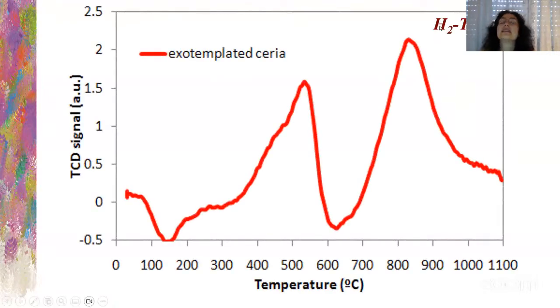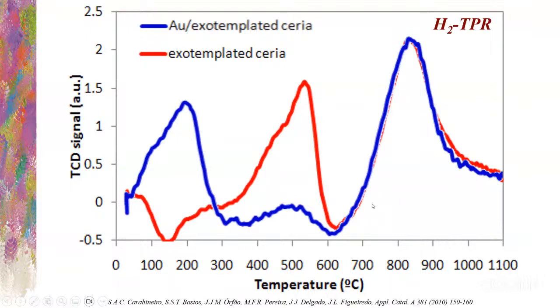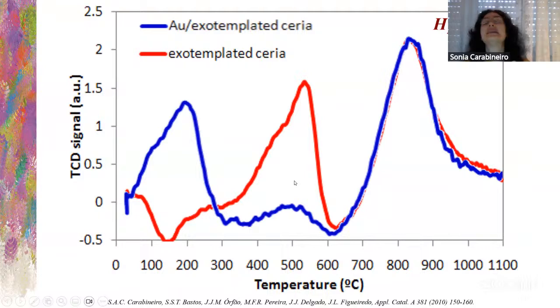If we compare here the TPR, the temperature programmed reduction, for the exotemplated ceria, as I said before, this is the bulk. The bulk oxygen is reduced at higher temperatures. Around 500 is the surface oxygen reduction. So if we add gold to the sample, what happens? The bulk oxygen peak remains the same, but the peak of the surface oxygen is shifted to lower temperatures, which means that the surface oxygen is reduced more easily at lower temperatures. So this sample can be more active, and we will see that indeed that was the case.